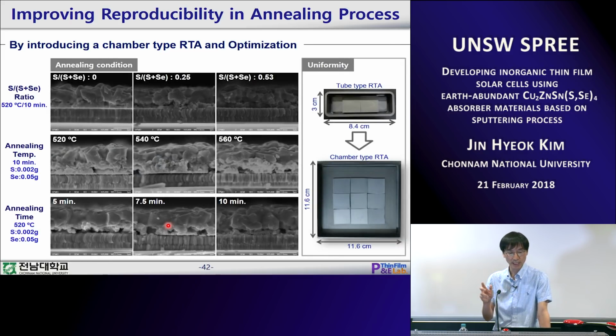After changing to the chamber type, we changed the sulfur over sulfur plus selenium ratio, the annealing temperature, and the annealing time, so there are many process parameters to optimize the annealing process. Also, by changing the furnace type from tube to chamber, we could improve the size of the annealing atmosphere. When we used the tube furnace, we used a small graphite box, like 3 centimeters by 8 centimeters. But after using the chamber type, we could enlarge the graphite box. It's 11.6 by 11.6. That means we have much better uniformity during the annealing process. So I think this makes it much easier for us to control the annealing process.